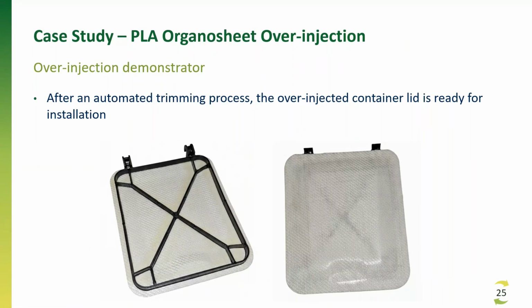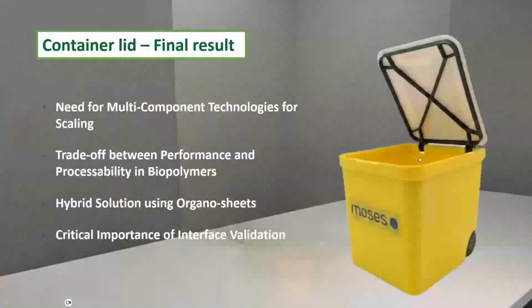Once we finish the over injection, we take the part out and cool it down, so that we avoid any possibility of it separating. We make the PLA strong again, let's say, and with this we can use the part. This is the final part that we have made, and during these weeks, what we have been doing and demonstrating is that the lid is working, and we have been able to process it and manufacture a product with these three components. And once we heat up the material, we can remove the overall ribs, and we can mill these ribs and use them again for another injection molding.